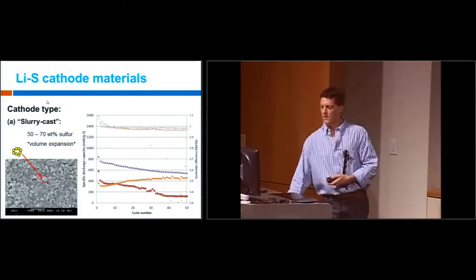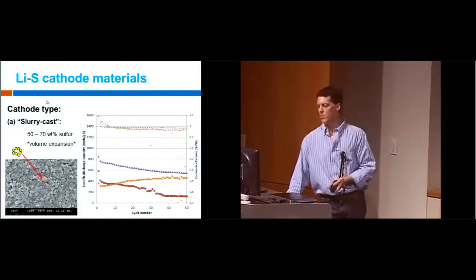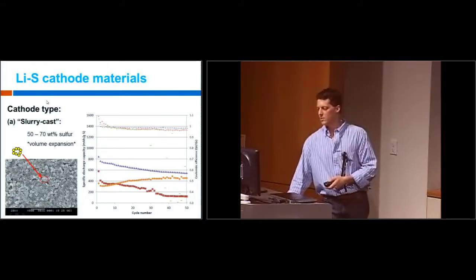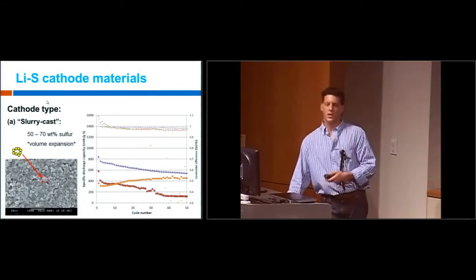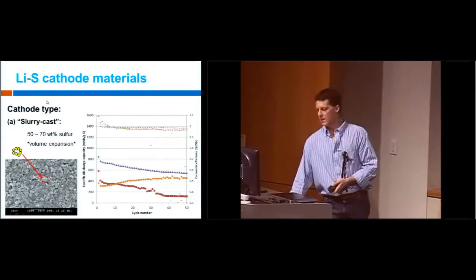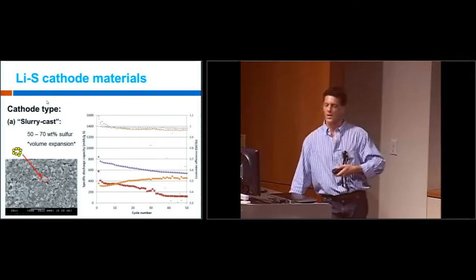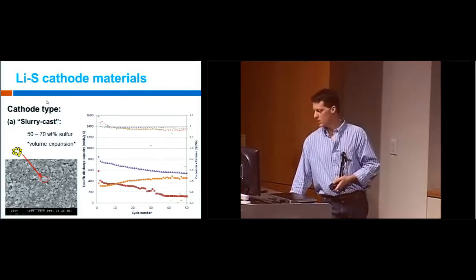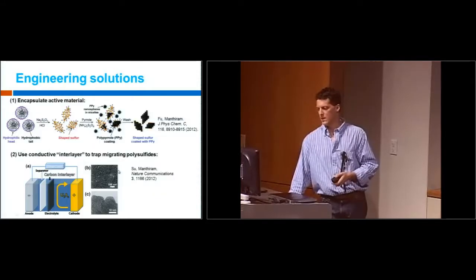And you can see that even though the nominal theoretical capacity is a little bit more than 1,600 milliamp hours per gram, you get much less than that out of it, and the capacity declines. This is the number of cycles. This is a charge and a recharge, and as the number of charge and recharges goes up, you lose a lot of capacity. So this is not a very ideal configuration.